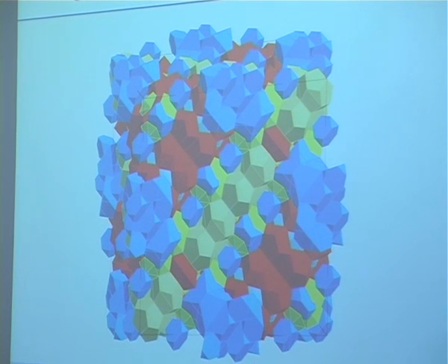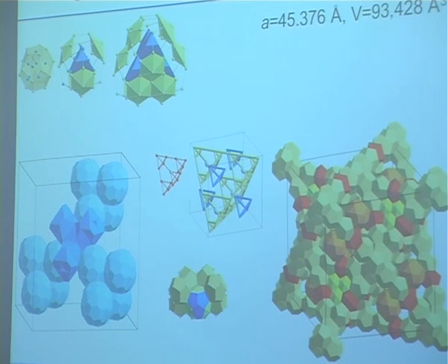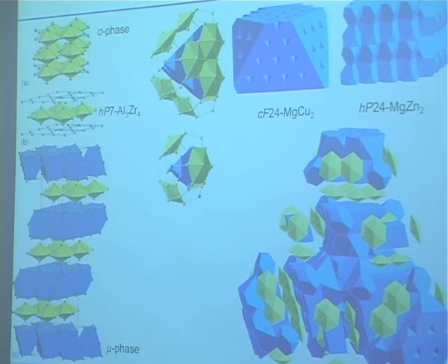And that's a structure. And we see what we need is just the best arrangement of some clusters, and each cluster has a given chemical composition which fluctuates around the mean value of this compound. But these clusters are not stable entities. These are structural units, because we can describe the same thing either as a packing of these fullerenes and Friauf polyhedra, or in this way. So a cluster is just a way to better describe a structure, to identify the structural building elements. And some of these clusters may have, of course, different bonds inside than outside, but that's not always the case. Well, to summarize: all these compounds are found in the system aluminium, copper, tantalum, and modules of these neighboring compounds are used to build a huge structure.